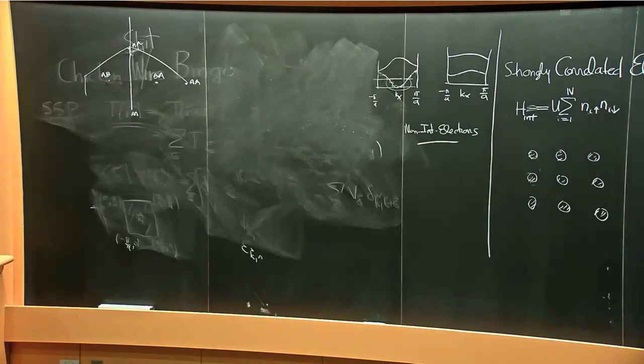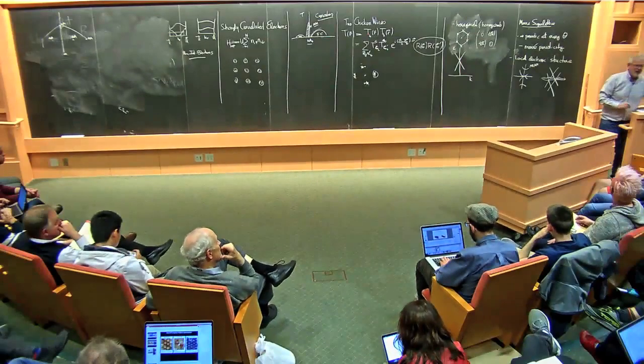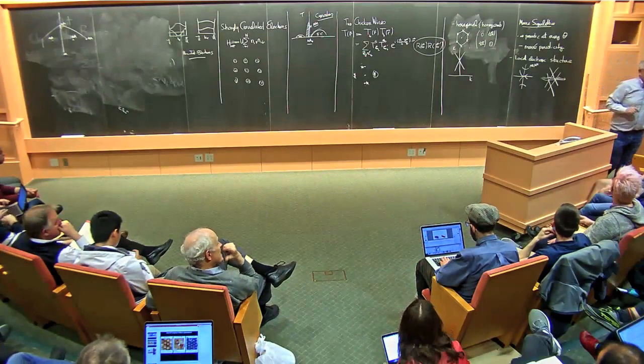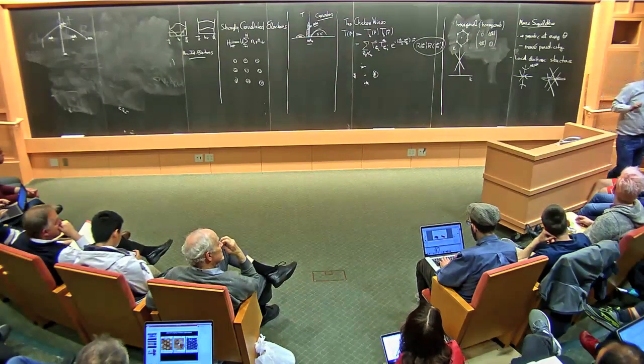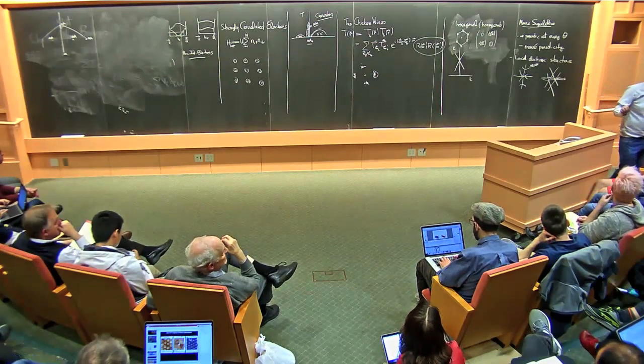Go ahead. Is it obvious you don't move the layers slightly laterally to get the registry better and optimize the electronic structure by slightly distorting the lattices? You do slightly distort the lattice, but not very much. And it's a quantitative effect you can easily take account of that I'm ignoring.